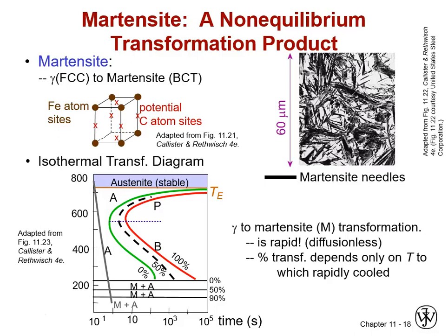And that's where we get what I'd refer to as retained austenite, where you can have face-centered cubic iron austenite at room temperature. It has not formed pearlite, it has not formed ferrite, and it hasn't formed martensite. It's totally stuck. That's a very unstable phase. And in fact, it can be induced to form martensite simply by giving it a little bit of impact. In cases where we want to form 100% martensite from those, we'll actually quench to below room temperature. And if you've ever heard of cryogenic quenching, that's why you do it.